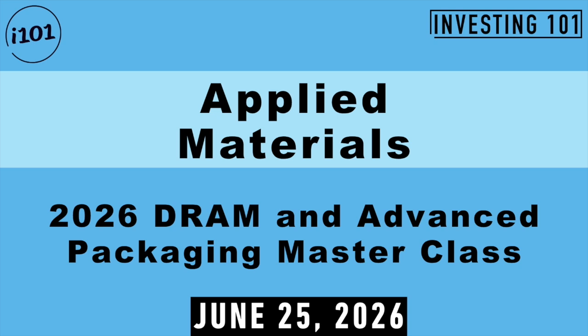The junctions are deep and narrow, and reliability depends on keeping the dopants contained to the target regions of the transistor and uniform across all the transistors on the wafer. In 4F² DRAM, traditional high-temperature anneal processes are not viable because they damage the delicate capacitor structures. To solve this, Applied has developed a low-temperature selective epitaxy that grows doped crystalline silicon only on the targeted region